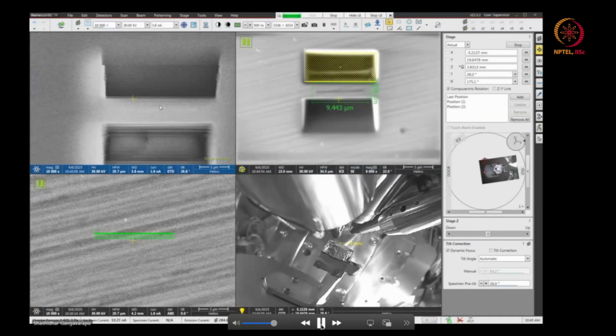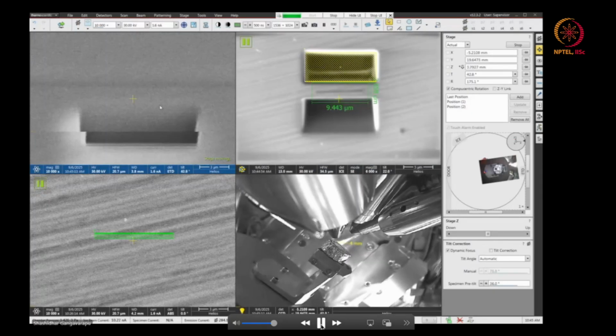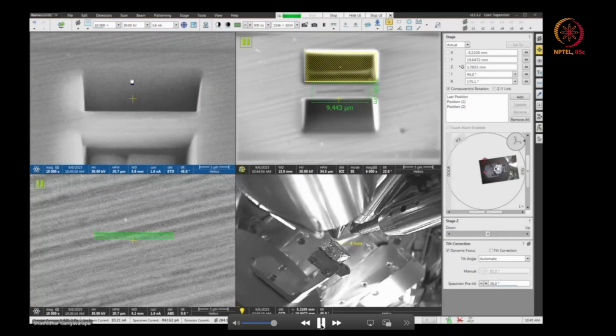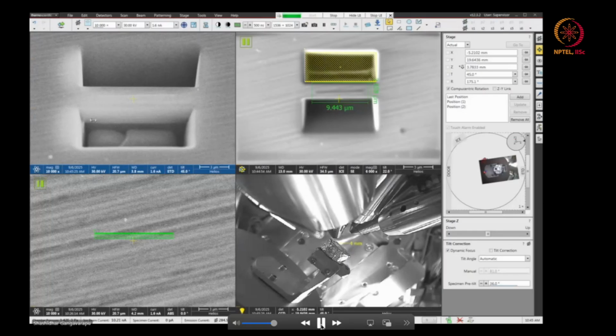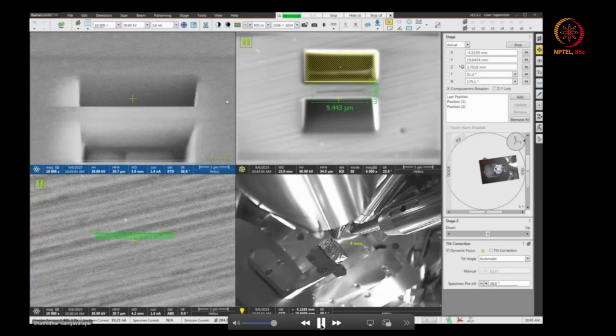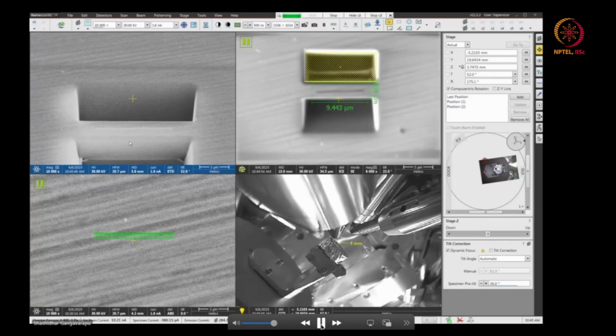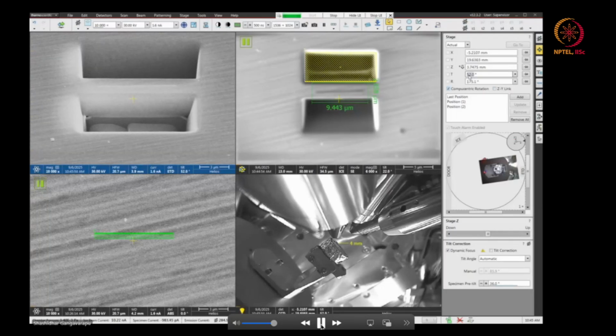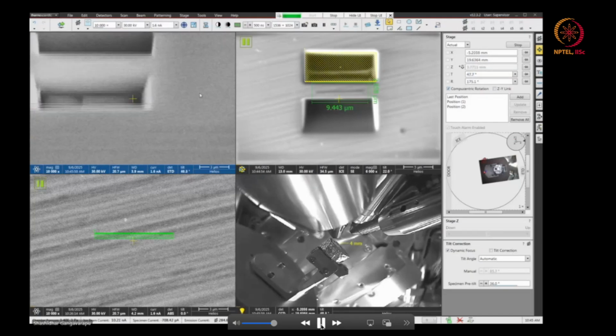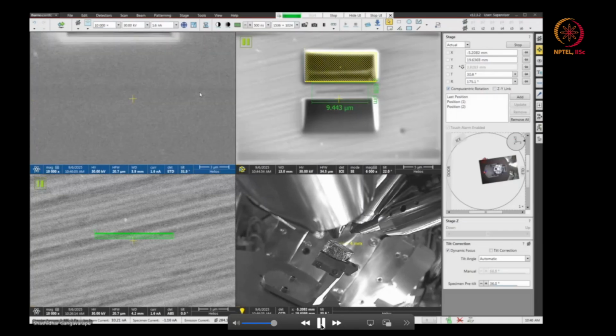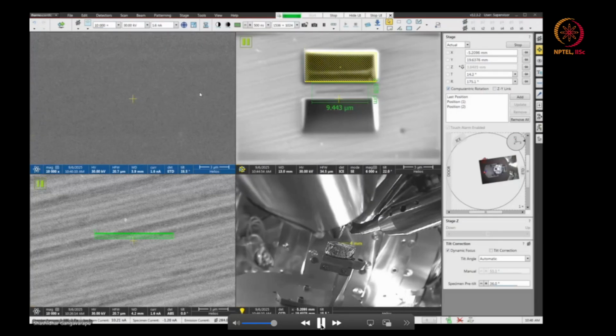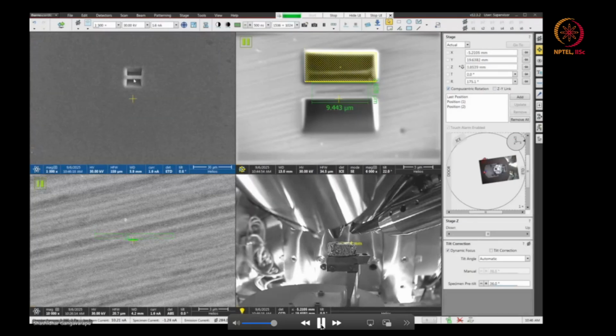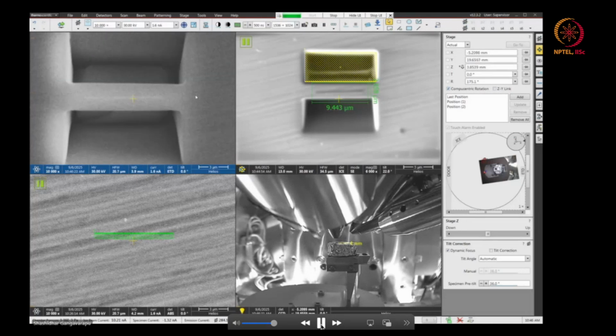Now I am tilting to 45 degree to check that it cut perfectly from both sides. I am using the beam shift to bring my region of interest to the center, and you can see that the sharp line is there, so it cut from both sides. Can check at 52 degree as well. So it cut perfectly. Now I will come back to 0 degree. Now you can see in the E-beam window that on both sides it cut perfectly. So the trenching part is done.